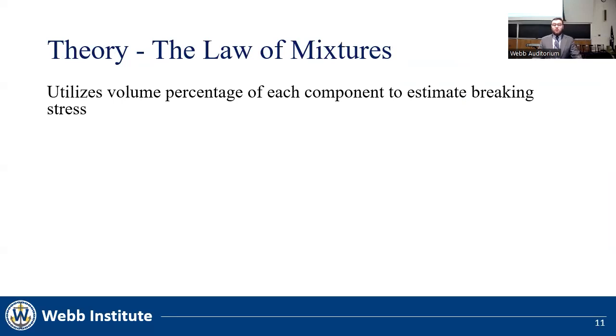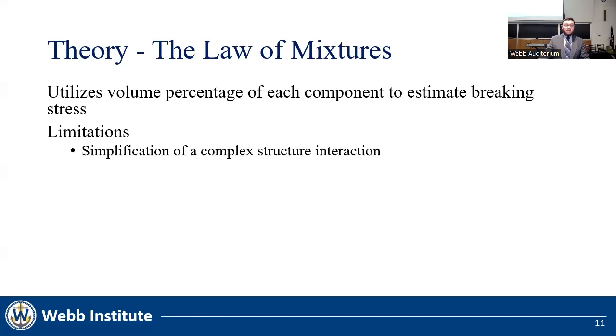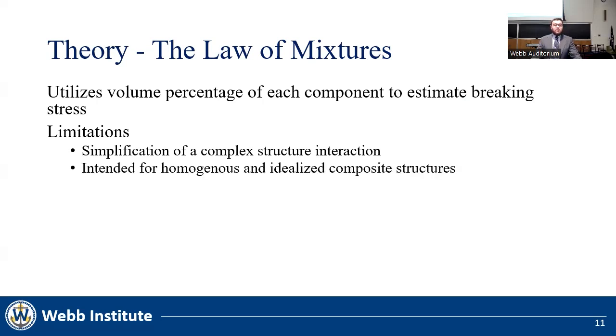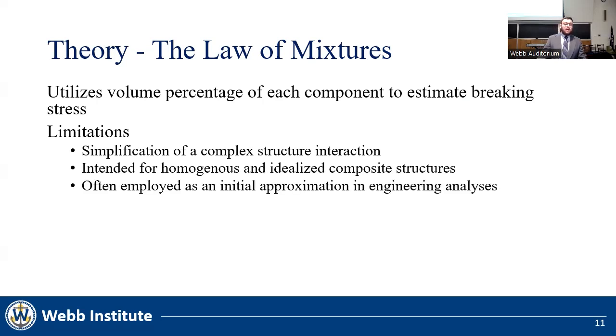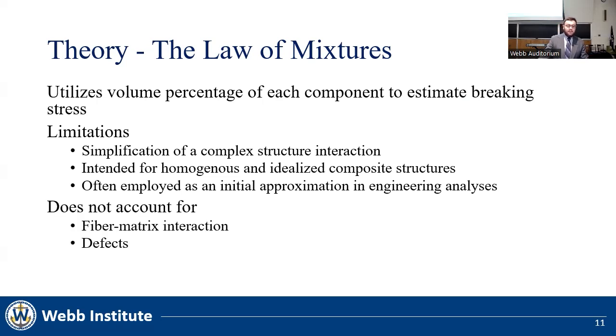The law of mixtures was utilized to provide the material properties of the overall composite from individual fiber and matrix properties. This utilizes the volume percentage of each component to estimate the breaking stress. Some limitations of this law are that it is a very simplified model of a complex structure interaction. It is intended for homogeneous and idealized composite structures, and it is often employed as an initial approximation in engineering analysis, which is how I used it here. It does not account for the fiber matrix interaction or any defects in manufacturing.